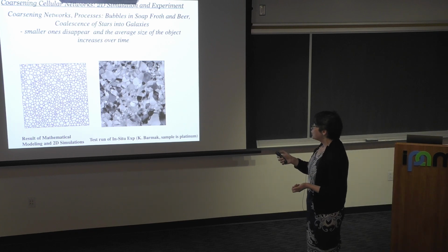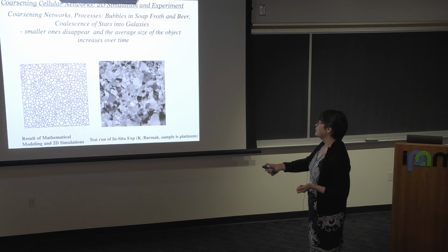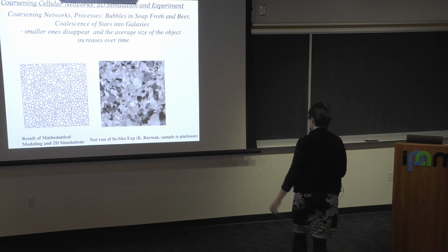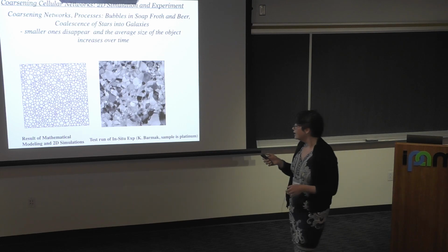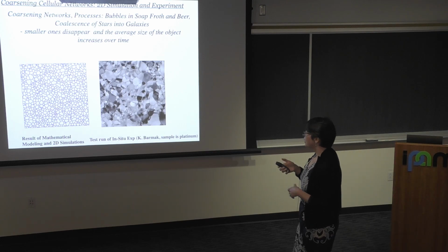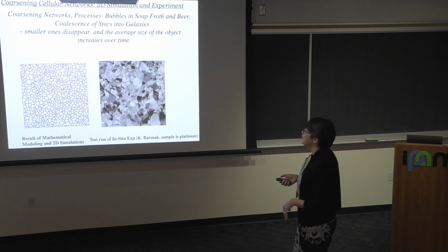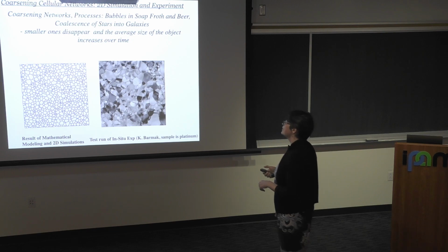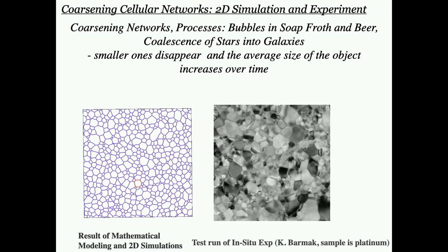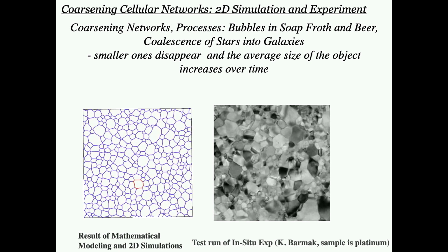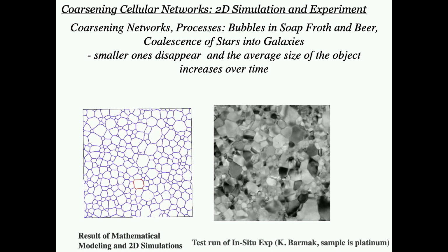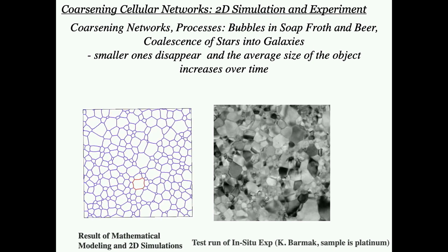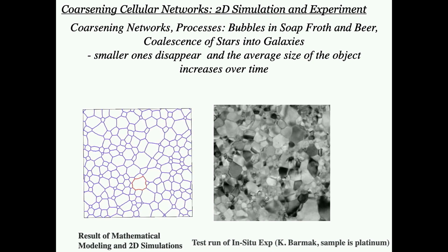So in general, in pure materials, grain boundaries are non-equilibrium defects that carry an excess of positive energy. So when you anneal a material, for example, to a higher temperature, the microstructure starts to coarsen. And here are numerical simulations of that. So what we observe is that the smaller grains disappear, the average size of grains increases with time, and the total number of cells decreases with time. So the system coarsens.